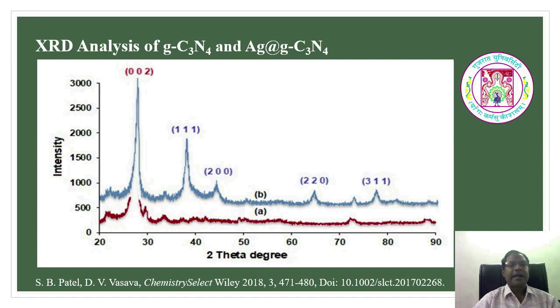Now here it is the XRD analysis of graphitic carbon nitride and Ag graphitic carbon nitride. XRD is utilized to confirm the crystalline structure of the material and also the size of the nanoparticles. So here the figure showed a broad hump at a 2 theta value of 27, which is the XRD pattern of the graphitic carbon nitride. It can be clearly observed that typical XRD peaks of graphitic carbon nitride can be seen, and all the diffraction peaks are in good agreement with the hexagonal carbon nitride structure, which is in accordance with the literature.